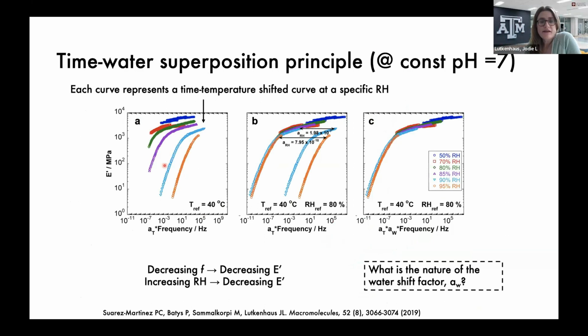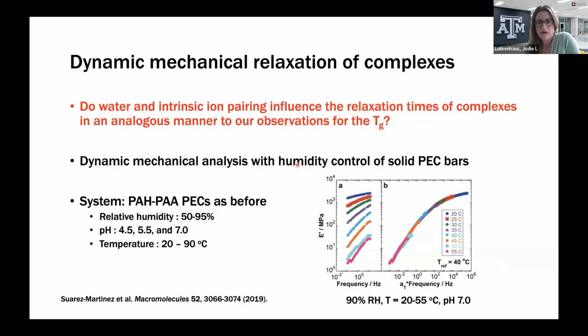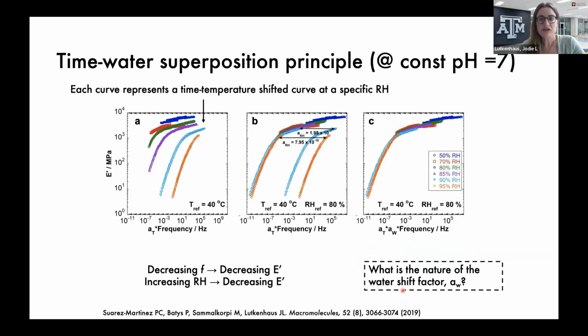And with this data, we performed time temperature superpositioning. So here's an example of storage modulus taken at all these different temperatures. And then we can horizontally shift them using superpositioning, where AT is called a shift factor. And that shift factor AT follows an Arrhenius law.